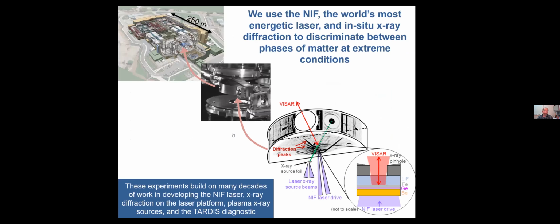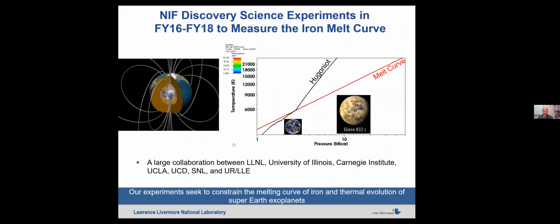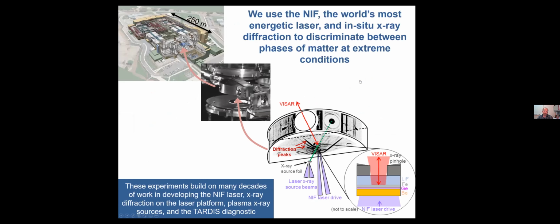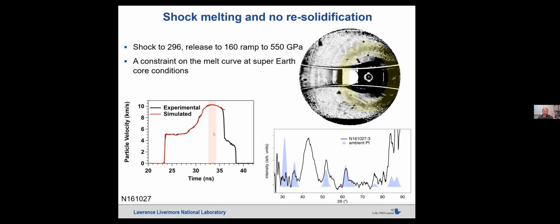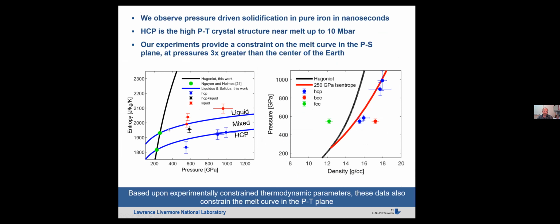What Burkhart's referring to is the fact that if you follow an isentrope through a melt curve, so this is now following the trajectory of the material, this material gets stuck on the phase boundary and is buffered by the phase boundary. It's in a mixed phase until it gets off that phase boundary. So that's actually consistent with our interpretation of this data, in that at constant entropy, along this melt curve, you would be stuck on the phase boundary for a large pressure range, even larger than I would say that EOS would suggest.